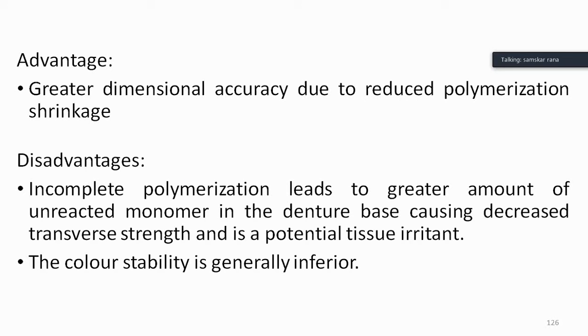The advantage of this is it has greater dimensional accuracy due to reduced polymerization shrinkage, and the disadvantage would be incomplete polymerization leading to a greater amount of unreacted monomer in the denture base, causing decreased transverse strength and being a potential tissue irritant. So the main disadvantage of self-cure acrylic resin is there is a very small amount of polymerization, which will lead to decreased strength. The strength will be less. That's why for definitive restoration or for permanent prosthesis, we do not use self-cure acrylic resin.